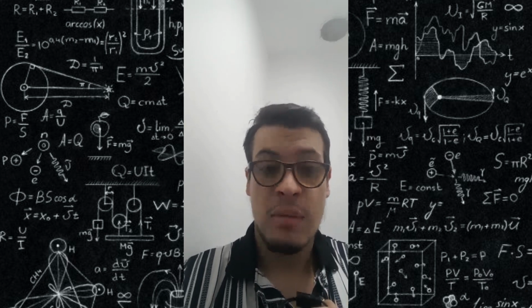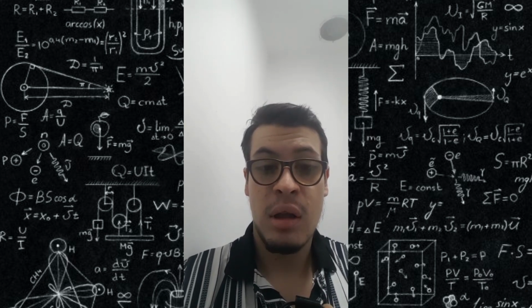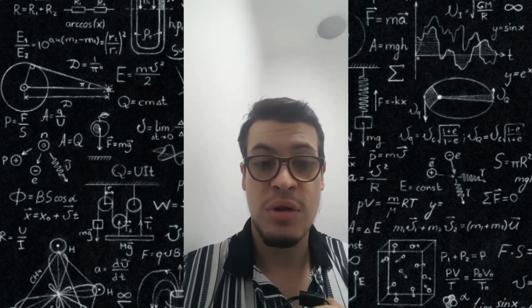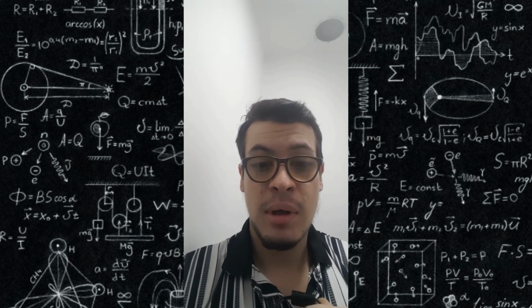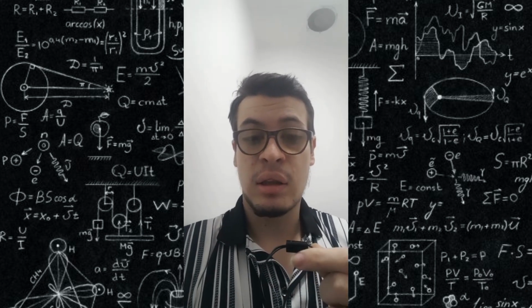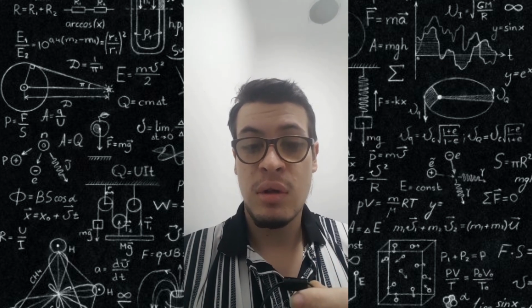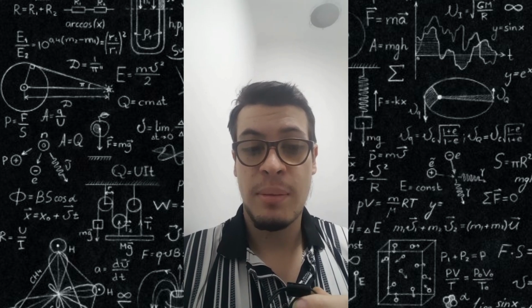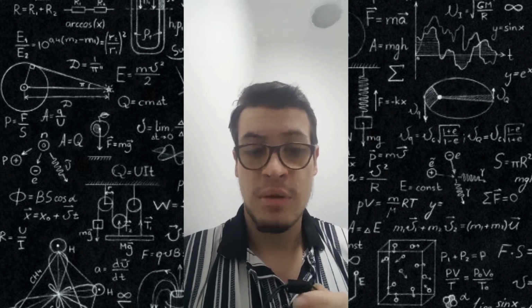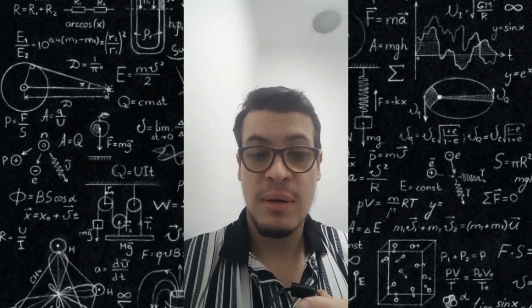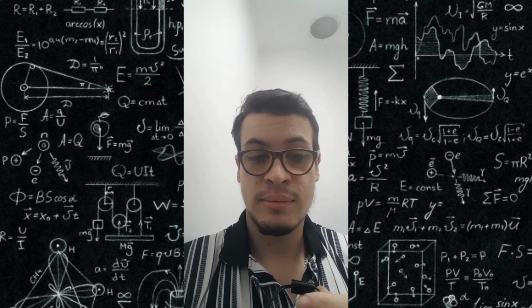application of the magnetic particles. A magnetic particle suspension is then applied to the surface of the part. The suspension contains small magnetic particles that are attracted to any discontinuities or cracks in the surface of the part. 4. Inspection. The inspector examines the surface of the part for any visible indications or defects.